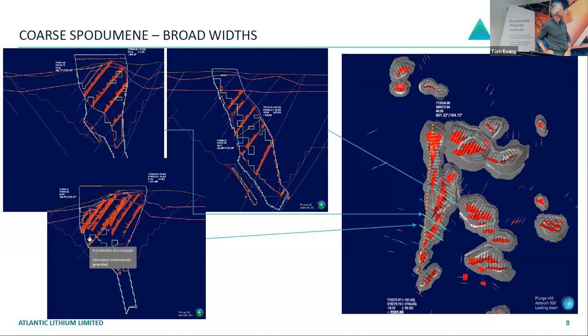And then in the Ewoyaa main section, in this lens here, that's roughly 500 meters long and at surface 100 meters wide. So it blows out into this wine glass shape. And there are a few other pegmatites around the world that actually show this as well. So it must be something to do with those emplacement controls, structural controls, pressure, temperature scenarios around that emplacement. But quite interesting to see that same wine glass shape, which is also really useful from a mining point of view and strip ratios.